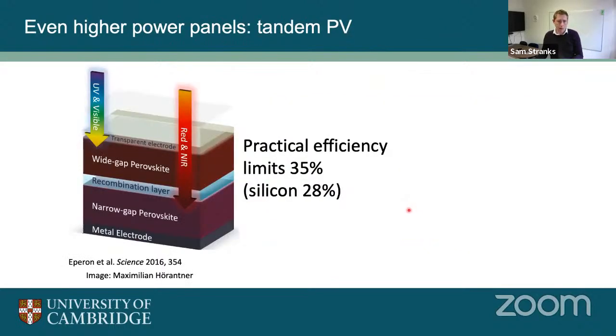But because we can change the color, one of the most exciting opportunities for these cells is actually to push to higher efficiency. And so I talked briefly about that there is a compromise for an efficiency limit, and in fact that efficiency limit for just one absorber ends up being around 30%, the thermodynamic limit for conversion of the sunlight to electricity. But we can do a trick where we can actually layer 2 cells together. So this is what's called a tandem solar cell, where we have a top cell which is harvesting the bluer wavelengths, so the blue and some of the green gets absorbed by this top cell, and then the redder wavelengths pass through to the bottom cell, and they're absorbed in the bottom cell here. And these work in series, so actually this combination here pushes the efficiency limit from something like 30% to more like 50%.